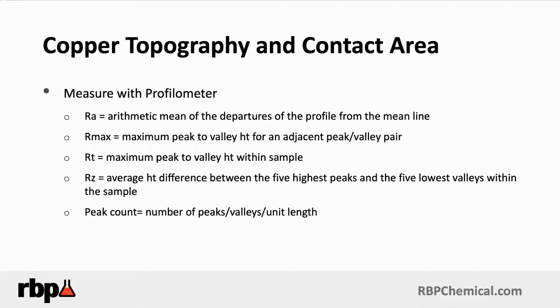Now, there are a number of ways to look at how the surface is set to provide good adhesion. One of those is topography, micro roughening, which you just can't see. Photoresists today have a different type of technology. They used to have a significant amount of adhesion promoters in there, not so much anymore. So adhesion is really dependent more on how you prepare the surface, both mechanically, in other words by roughening it up, and also by treating it chemically, and also enhancing the lamination of the resist to the surface in the lamination process. I'm not going to go into a lot of discussion about profilometry, but suffice to say, you have to have some mechanism of mechanical adhesion, some micro roughening. It's very difficult to put photoresist on and expect it to adhere over a completely smooth copper surface.